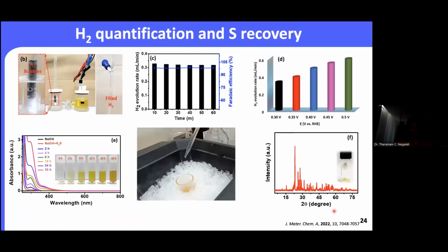And again, we have quantified this hydrogen as well, by both water displacement as well as online GC, and you can see that the hydrogen evolution rate is quite stable, and also the Faraday efficiency is almost 98%. And the hydrogen evolution rate is increasing with respect to the potential here. And to understand the polysulfide produced in the solution, we monitored simultaneously by UV visible spectroscopy, which confirms the lower order polysulfide.